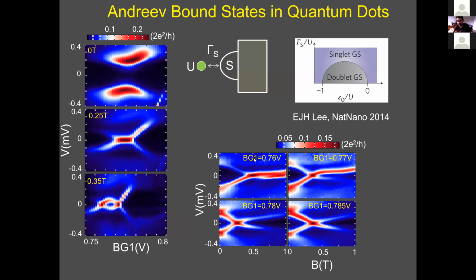Except look at this gate voltage of 0.76 volts for this quantum dot. You can see that for whatever reason, some uncontrolled parameters, the 0 bias peak forms here from the crossing of 2 levels, but they never split. It just keeps staying here and stays for a considerable energy of half a Tesla, which is about a millivolt of energy, just doesn't split, right? And so if you find this in your data, and you don't know much about Andreev states, you can say, well, maybe this is Majorana, right?